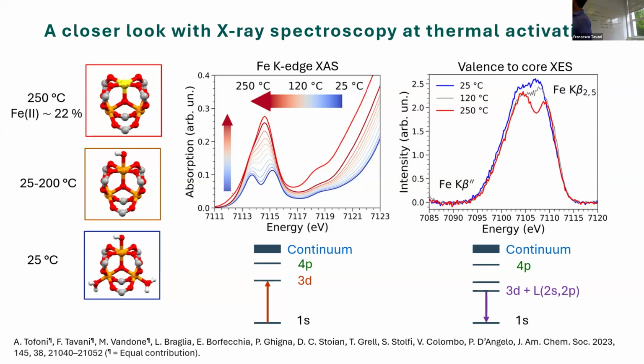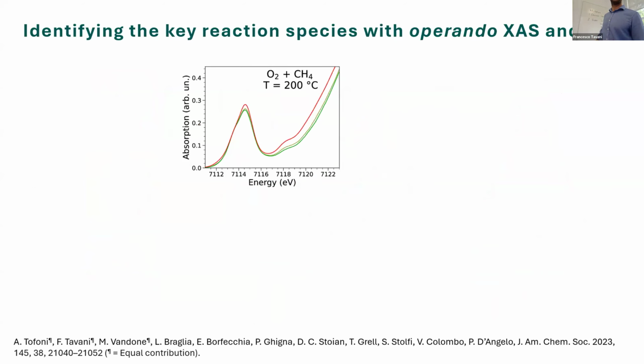So if we consider, for example, the XES spectrum in blue of the pristine MOF, this is quite different compared to the XES spectrum of the thermally activated MOF. So we have actually demonstrated, just by following the thermal activation, that these techniques are sensitive to change in local environment. Do you have any idea where the other hydrogen comes from?